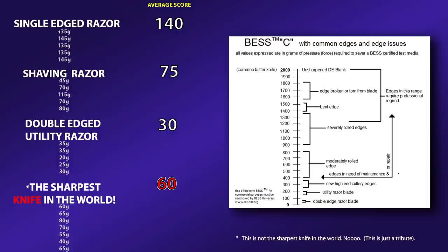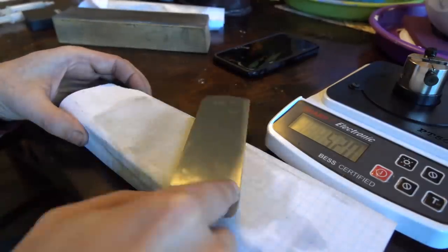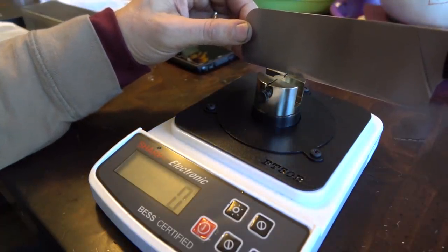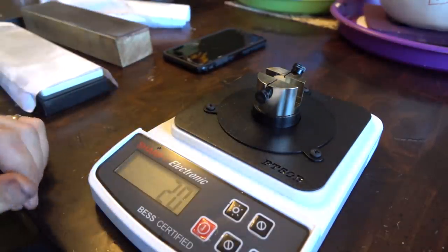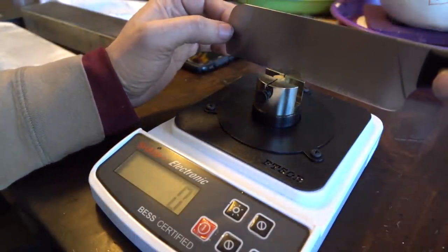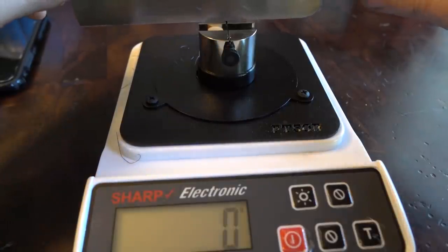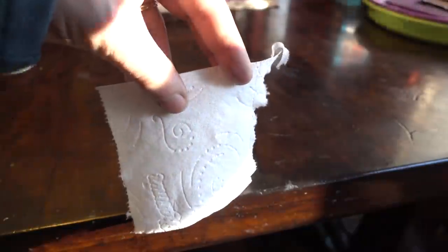What I've made is much closer to a straight razor than it is a chef knife, and I'm wondering where a straight razor would come out here on some testing. It'll be interesting to see that. I feel like I can get slightly better results, or at least I should be able to. I'm putting some 0.5 micron compound here on a piece of paper on a sharpening stone, and then doing some more sort of honing and stropping. And I got some pretty consistent results from 20 to 30 near the first two-thirds of the blade. But at the heel, there's still a spot that comes in around 55, and I even got 110 there. So I don't know. That probably has to do with my skills sharpening.